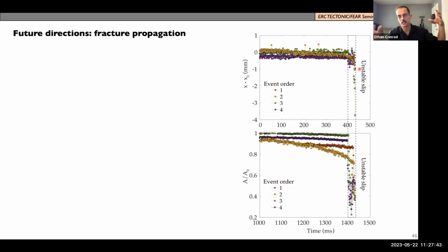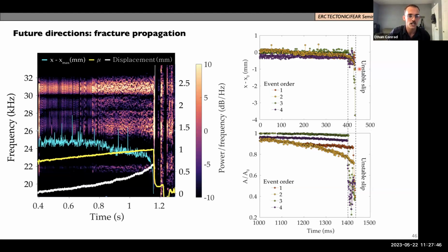And we see the radial shrinking of the melt patch, and pairing that with acoustic emissions, there seem to be characteristic acoustic emissions associated with these precursory phases of rupture propagation, where we have very slow propagation, a much faster propagation, and a change in the AE spectrum. The white here is showing the displacement, which also changes in its behavior. The rate of change also changes as the AE spectrum changes, and then ultimately you have the event. So this is kind of just a teaser for the work that can be done in the future.